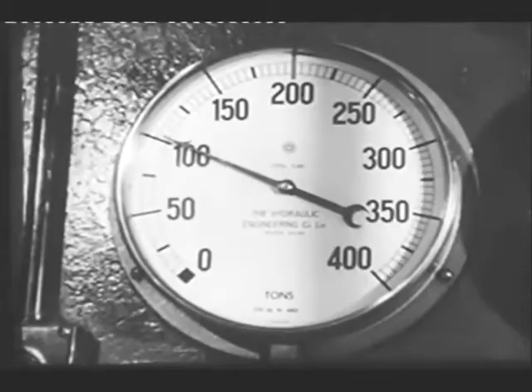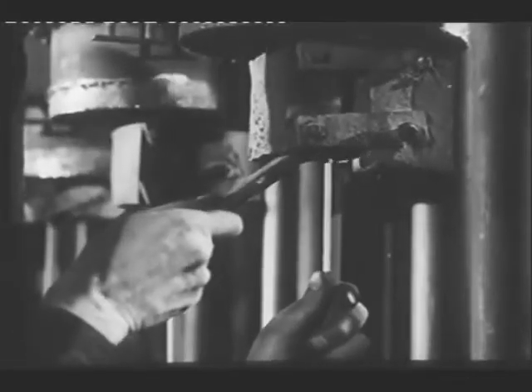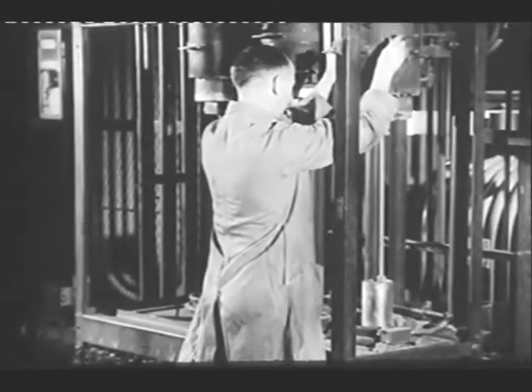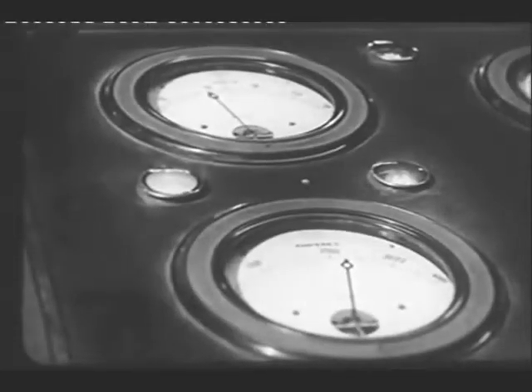The mold goes into a hydraulic press, and a pressure of about 100 tons is applied. When withdrawn from the mold, the metal is in bar shape, but as yet it is very fragile. So the bar is now sintered. It is heated to a very high temperature by enclosing it in an atmosphere of hydrogen and passing an electric current of between 2,000 and 3,000 amperes through the metal. A temperature of 2,700 degrees centigrade is obtained. The tungsten now has a crystalline structure.